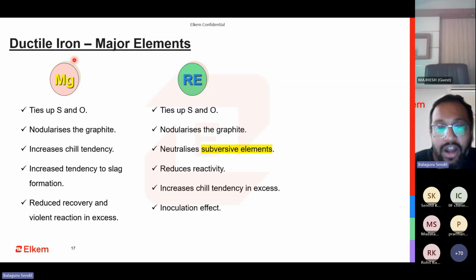On top of creating the nucleating site, it also creates an inoculation effect. So this is why completely avoiding rare earth is also not advisable. It is always good to have some amount of rare earth. That's why you see multiple grades of FSM and rare earth combinations. So it is always better to keep some amount of rare earth, and not completely eliminate it.